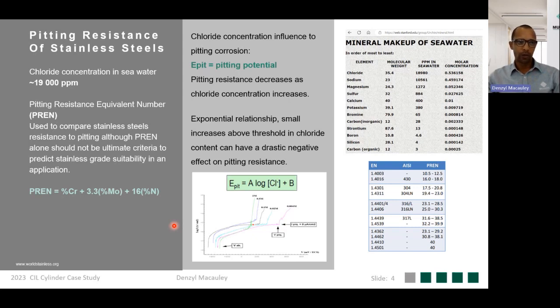What we further found is stainless steels are graded with regards to their pitting resistance on a PREN, which is a pitting resistance equivalent number, which I'll come to in the next slide or two. It uses the components that the stainless steel consists of, and there is a formula to calculate that number, and that number tells you how resistant a particular stainless steel is to chloride-induced pitting corrosion.